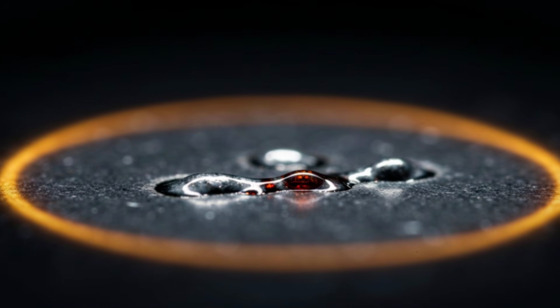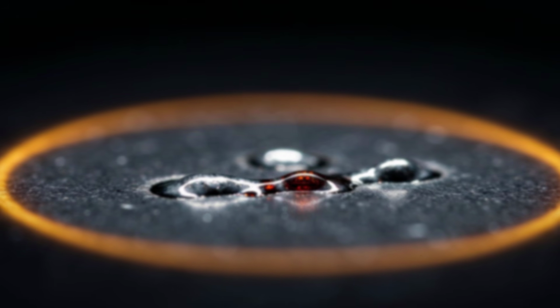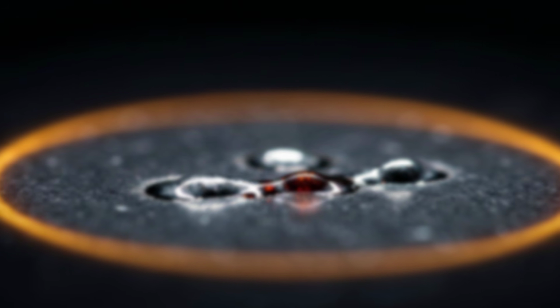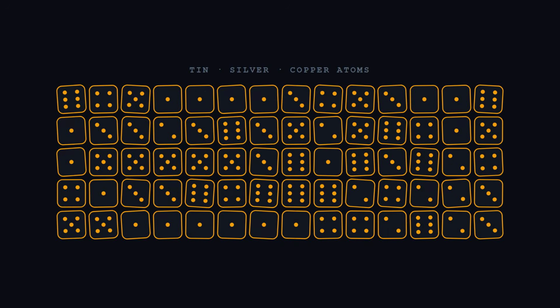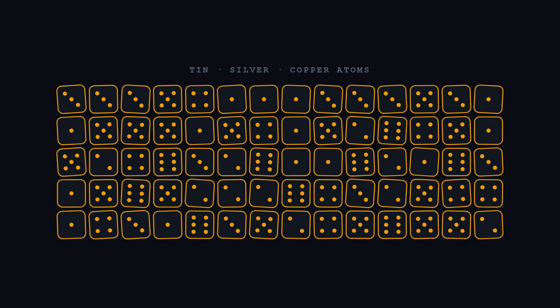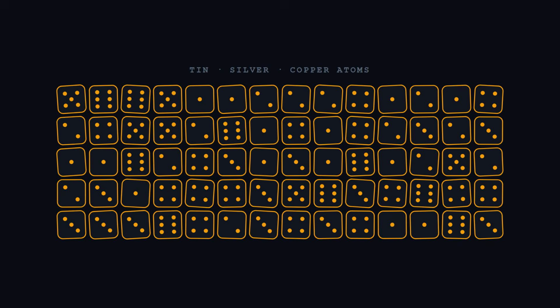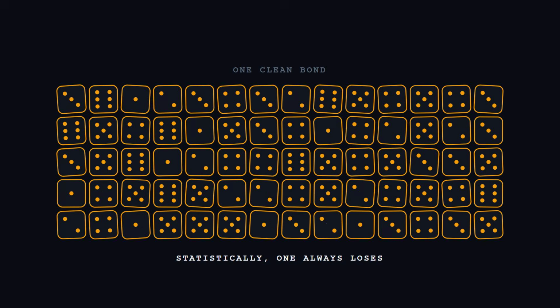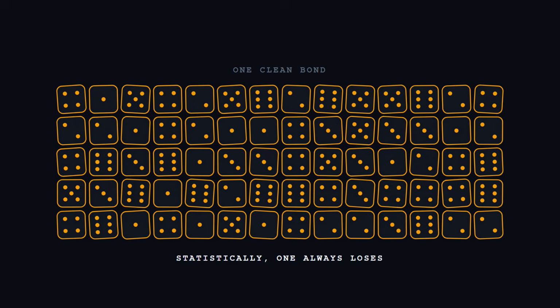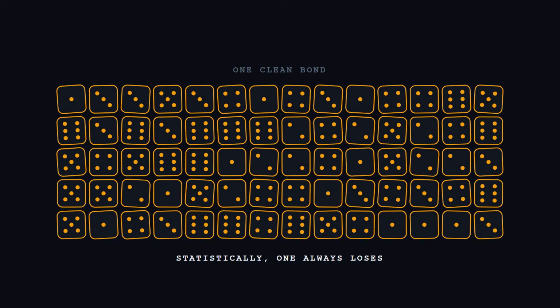Here's the part that's easy to forget. Even in the joint that worked, nothing was actually certain at the atomic level. You just forced billions of tin, silver, and copper atoms to arrange themselves into a lattice through heat, timing, and surface tension. What looks like one clean, deterministic bond is really the statistical outcome of an enormous number of individual, probabilistic events, pushed hard enough in the same direction that they behave like a certainty.